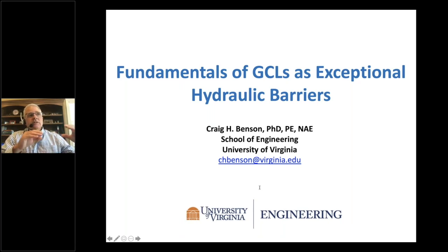But what's important is the swelling that occurs as the hydration process occurs. Whether we've got load on top and we get a large swell volume, or those bentonite particles themselves swell and fill the voids between them, that's going to occur regardless of the stress. So the swelling mechanism will occur at high stress or low stress, though whether it's manifested as a considerable change in volume at the macro scale of the bentonite will depend a lot on the stress. But what's important is that the chemical environment allow the granules to swell and fill the voids between them.